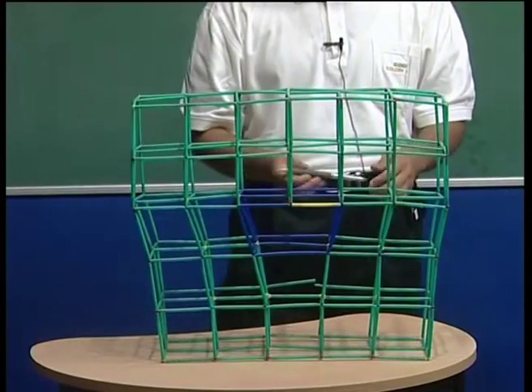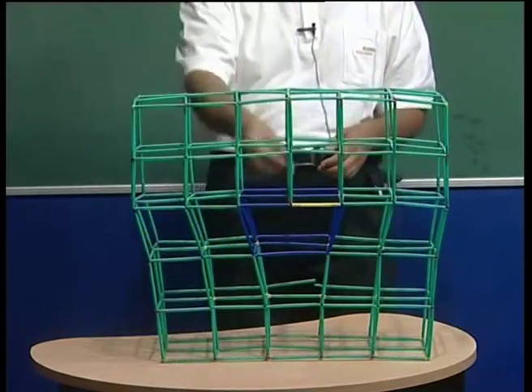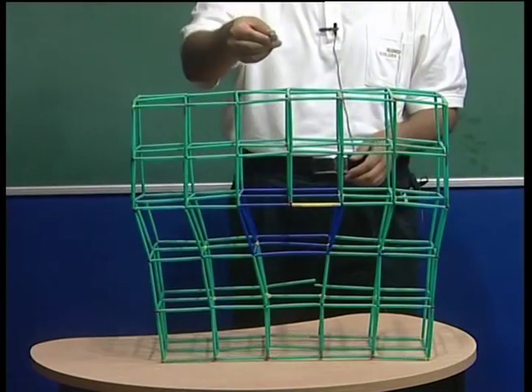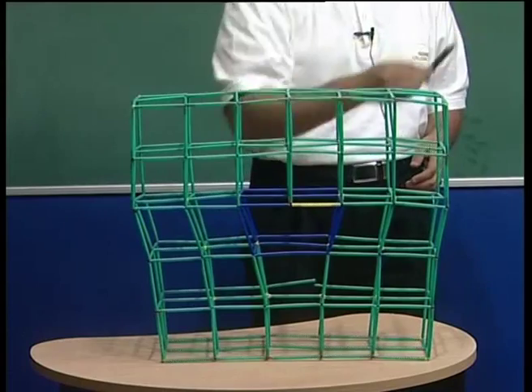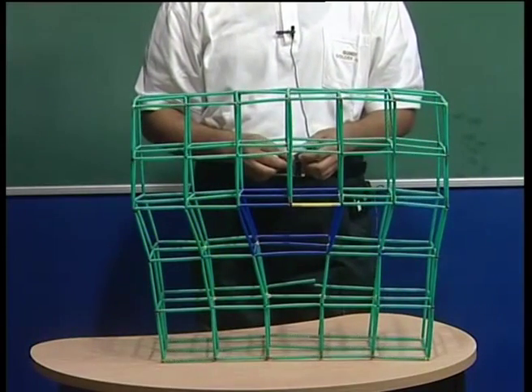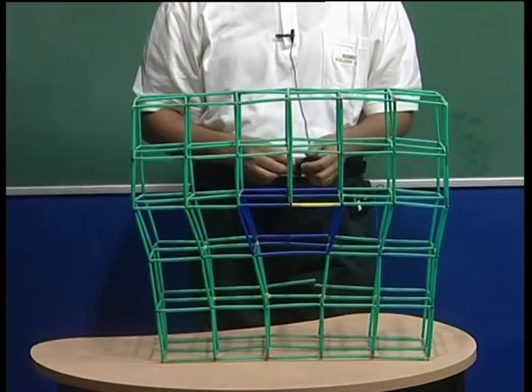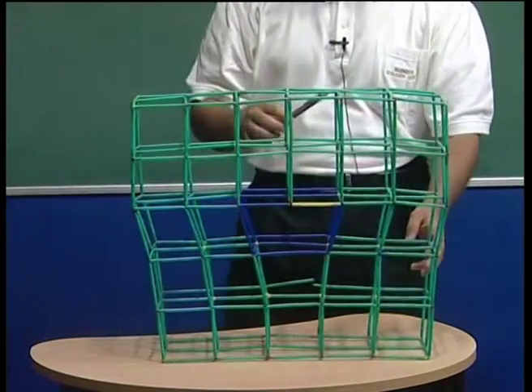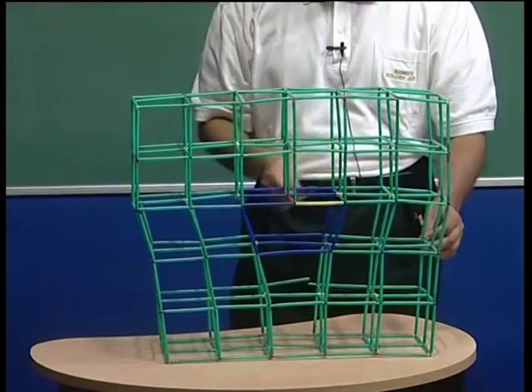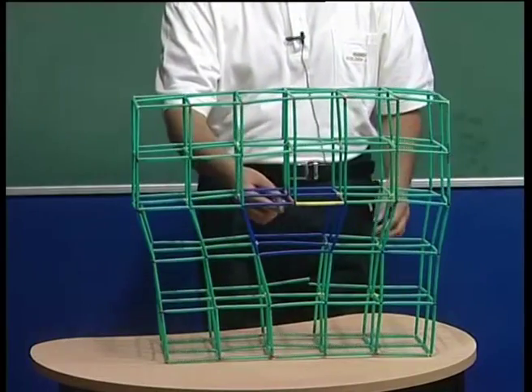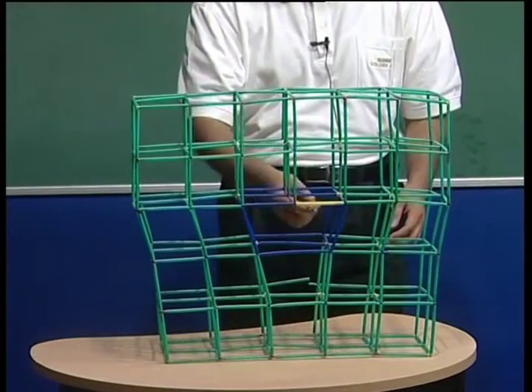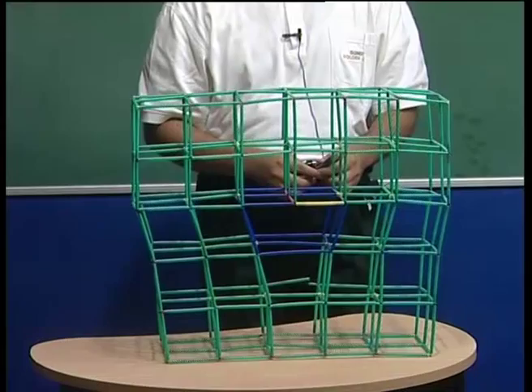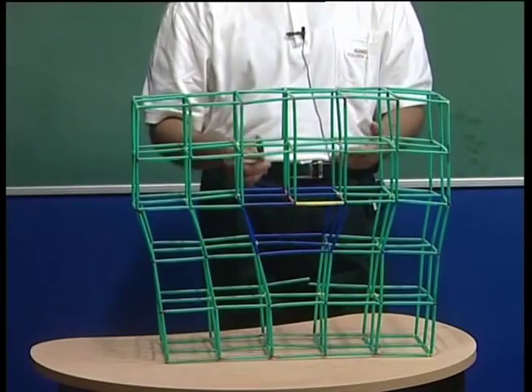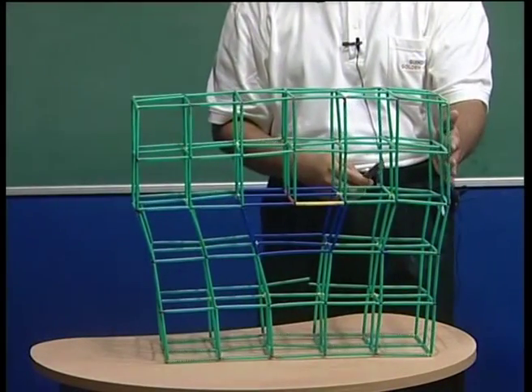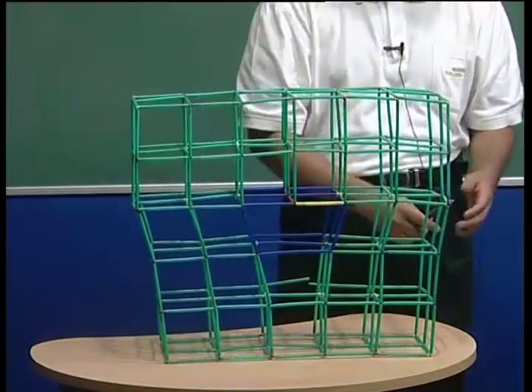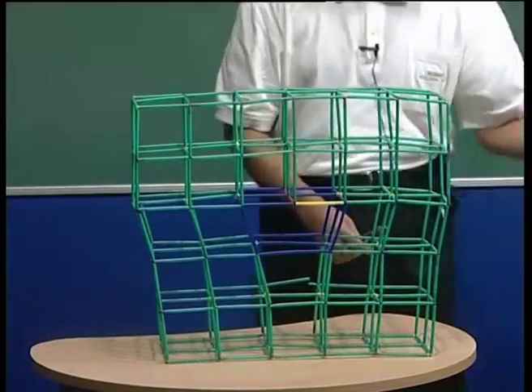In which direction would the dislocation line move? So this is my dislocation line direction. This dislocation line would move in the direction of the Burgers vector. So this is an important characteristic of the edge dislocation. So the B vector and the T vector define the slip plane, and the dislocation line in the presence of a shear would move along the direction of the Burgers vector. What would happen if it approaches a free surface? This extra half plane would come out and create a step on the free surface, as we shall see with some